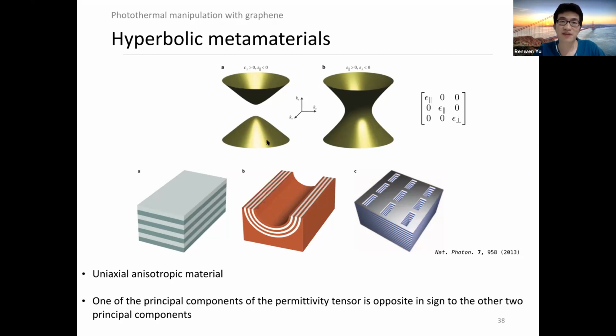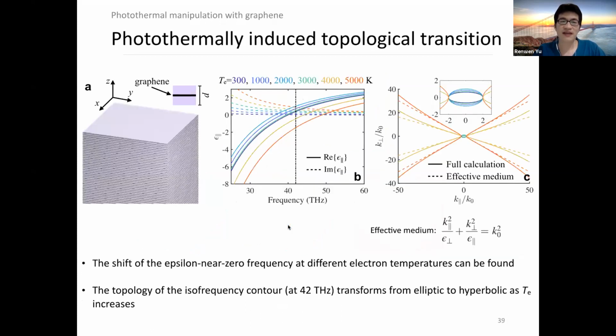And in order to have these materials, one can simply make a stack of dielectric and metal films, just like this, very simple. So here, I am considering these stacked materials composed of graphene and some dielectric materials. Due to the two-dimensional nature of graphene, the epsilon perpendicular, I mean the permittivity along the z direction, is a constant and is positive. However, when we look at the permittivity parallel, which is the in-plane permittivity of this effective metamaterial, we can see that it can change sign when we change the frequency. So it goes from negative to positive when we increase the light frequency.